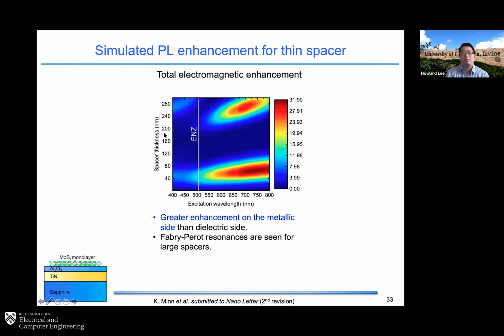So this is a simulation result for different spacer thickness from 0 to 300 nanometers with different excitation wavelength. You can see the ENZ wavelength here. The left-hand side will be the dielectric side, and the right-hand side will be the metallic side. You can clearly see that you have a stronger enhancement on the metallic side. You also see some kind of resonance here, a Fabry-Pérot resonance, because you're forming a metallic film at the bottom. As a result, you're forming a resonant cavity. That's why you have some kind of resonant enhancement here.